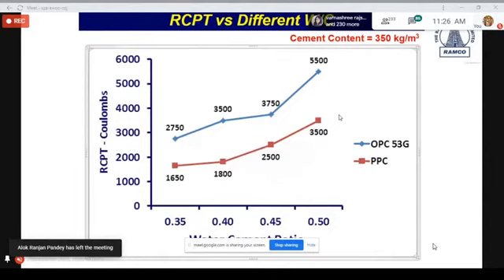Similar is the case for the rapid chloride permeability test. If you see, the permeability of water at lower water cement ratio and with blended cement is much better as compared to the concrete with ordinary Portland cement at the same water cement ratio. You can have a comparison of that. The cement content that has been taken is 350 kg per cubic meter. So this is also a durability test on concrete.